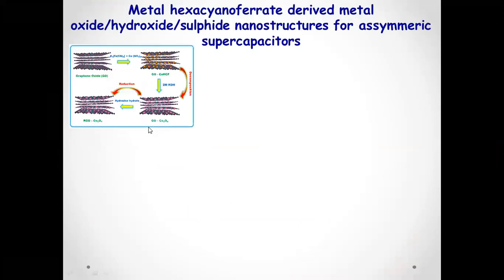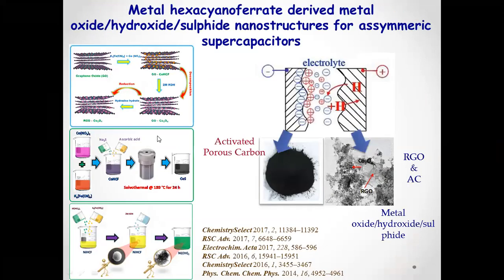Here we use, as I told you earlier, a different asymmetric system. One side you have a pure activated carbon. This is on the negative side. On the positive side, I have reduced graphene oxide containing some metal oxide, in this case cobalt oxide decorated graphene sheets. It was used as a positive electrode. And then this pure activated carbon prepared from the biomaterial is used as a negative electrode. So now I have an asymmetric system. Since both the electrodes are different, I should call it an asymmetric system.